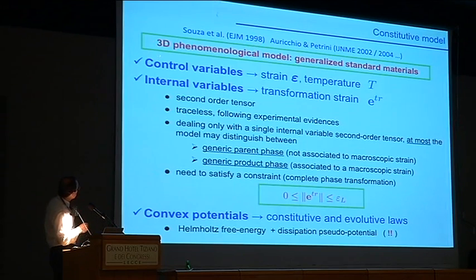It's a three-dimensional phenomenological model. It's based on introducing some control variables. As control variables, the model uses the strain, the second-order strain tensor, the temperature T, and uses only one internal variable. This is a second-order tensor, and it's named transformation strain, ε^tr, okay? So it's just one variable. It's quite, in some sense, a rich variable because it's a second-order tensor, but it cannot really capture all the micromechanical complexity.